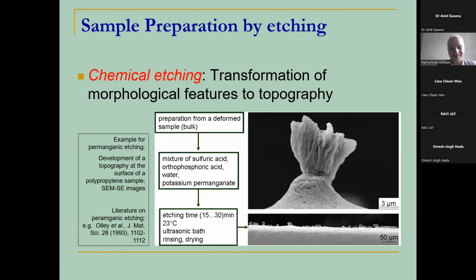So I will show you some more examples. It was a sample prepared by etching. It was polypropylene prepared by permanganic etching. The sample was sectioned, and then the bulk sample, after the sections were removed, was taken. It was treated with a mixture of sulfuric acid, orthophosphoric acid, and potassium permanganate, of course in water, the solution was made in water. This etchant was utilized, as you can see here, the lower magnification is here,